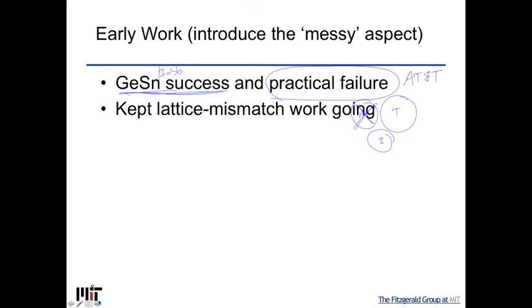So actually during this time, because of the knowledge that lattice mismatch was important, we kept that work going in parallel and decided to focus on silicon germanium. The reason we decided to focus on silicon germanium is that it is a model system where you could learn a lot, and it turns out we got kind of lucky in the sense that it was also a key alloy and engineering between silicon and III-Vs. It wasn't lucky in the sense that there were no other alloys in that range that could be used to put varying degrees of mismatch in, because other materials tended to be either III-V materials, which were a little less, here we're working on silicon in general.